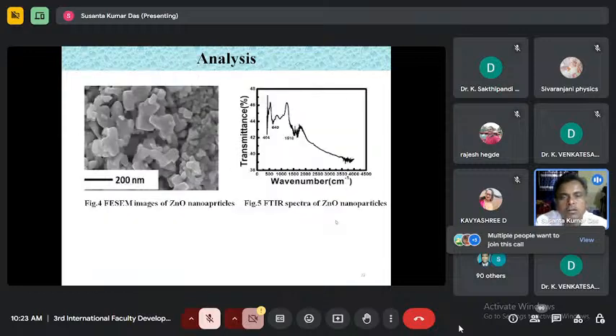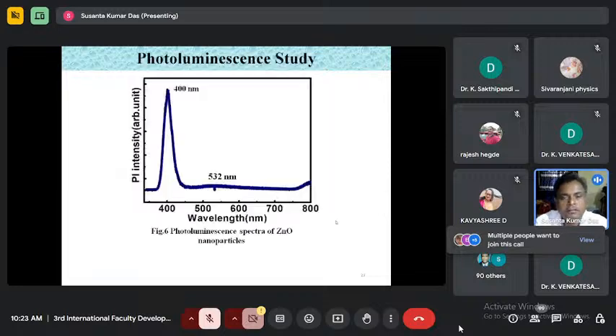And also we had gone for SEM, FESEM, and FTIR analysis. And there is a photoluminescence study we have done, PL study, to know the band gap. It's a wide band gap material. So the peak around 400 nanometers is the band edge luminescence. And there is a peak also at 532. This is the defect level luminescence. That is generally found in zinc oxide. So we found similar behavior.